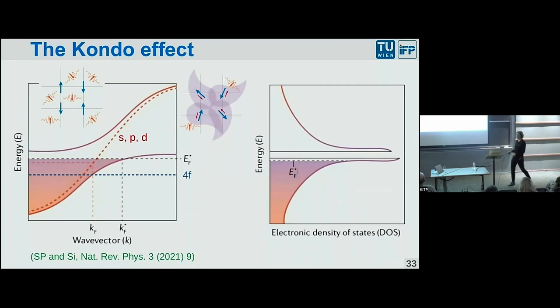These hybridized bands contain electrons that are very strongly interacting, so electrons that are not behaving with single-electron properties. They don't have the mass of a single electron, but the mass of like 1,000 electrons, 1,000-fold heavier in the solid. That means they find it hard to move, but the added value is their density of states. The density of states is how many states there are in one band, how many rooms, if you want, in Hilbert's hotel, there are per floor, and there are many, many, many rooms per floor near the Fermi energy.